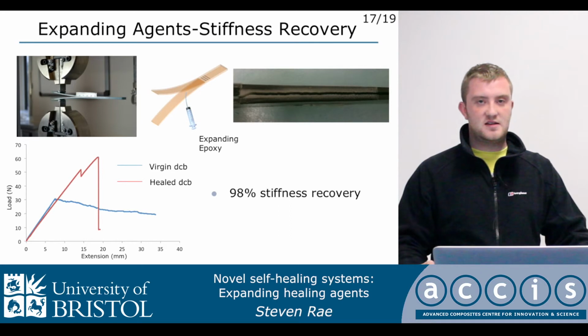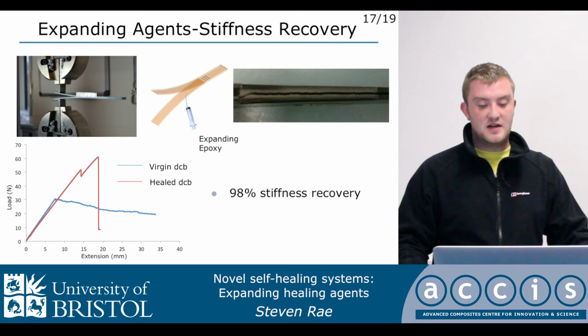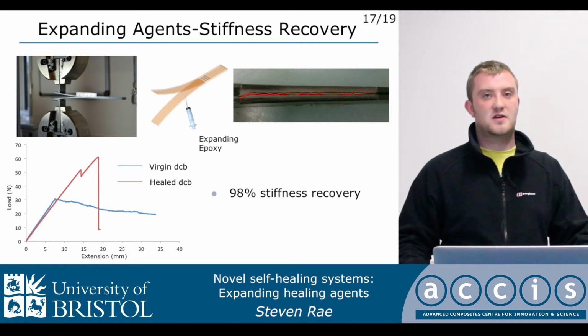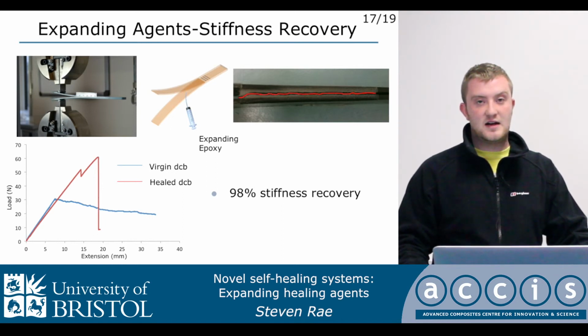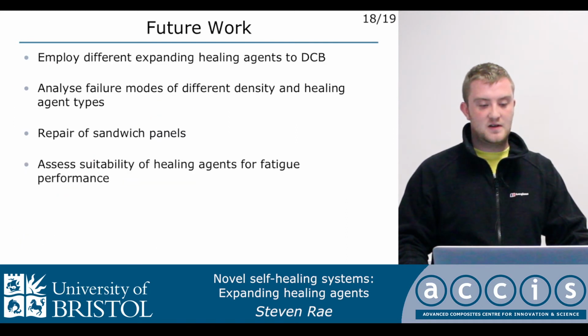So to actually test these healing agents in a more lifelike scenario, we've done some DCB tests. We get the baseline result as shown by the blue line on the graph, and then healed that with one of the expanding healing agents and tested again. As you can see, we've got a very close stiffness match and also it takes a much higher load. And in each case, we found there was cohesive failure of the healing agent rather than adhesive failure, which is ideal for self-healing systems.